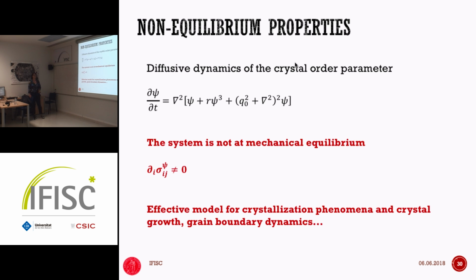How does this work when we have dynamical properties? So far, what I've shown is for the case where there's no dynamics. Now, when we put in dynamics, basically this order parameter field, this density field, has a diffusive relaxation dynamics towards whatever equilibrium it can reach, right? So it has an equation of this form. And what we have been able to show is that when you have this equation only for the order parameter, without constraining the stress field, it is not going to follow mechanical equilibrium. So the stress is also going to evolve, which means that the mechanical properties are going to depend on the evolution of the density field.